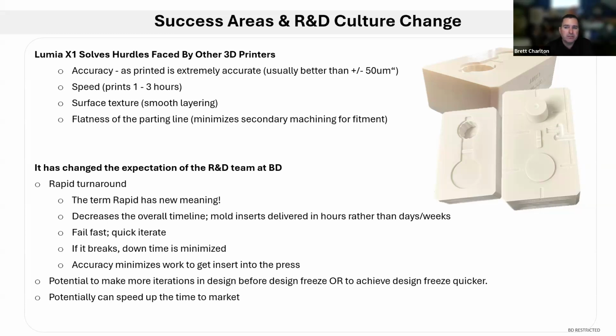We had transitioned to producing our rapid molds with direct metal 3D printing due to the longer lifespan of the metal printed tooling. The direct metal process wasn't much longer than the SLA, and we were assured of the mold's durability. If you're going to take 2 or more days for mold fabrication, you want to make sure that molds produced will at the very least yield some molded parts that you can provide to the requester. However, the Lumia X1 has changed all that.